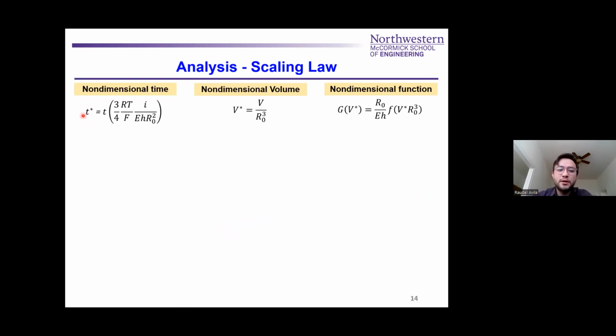So T star is going to be our non-dimensional time variable. It's going to be equal to the time variable, and then we have a coefficient in front of the time with units of 1 over time. In this case, this term groups the electrochemical part. We have the influence of the current, we have the membrane modulus, thickness, and radius squared. So this gives us units of 1 over time. Then our non-dimensional volume, we normalize by the radius of the membrane cubed. And in the same way, we normalize our pressure function by the radius of the membrane over the modulus times the thickness. So we have this geometrical coefficient, and then we multiply it by this pressure function here.